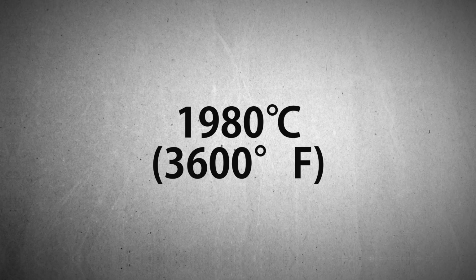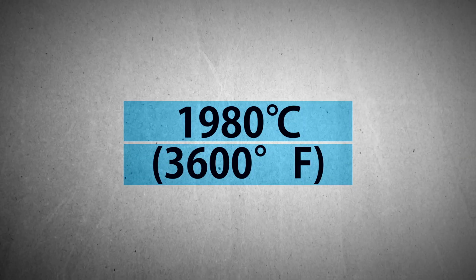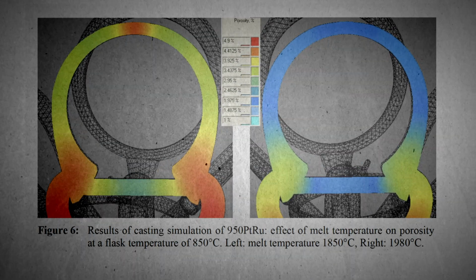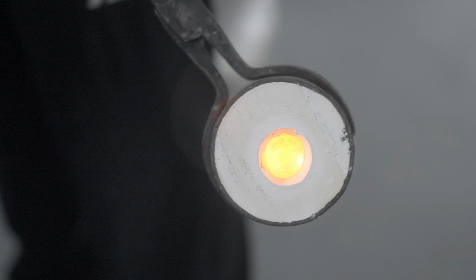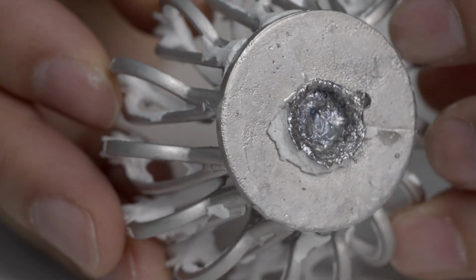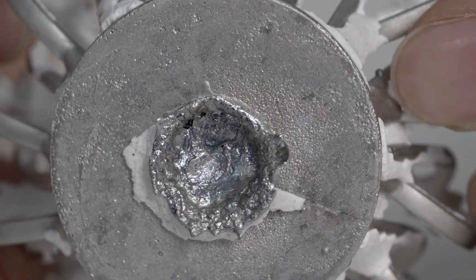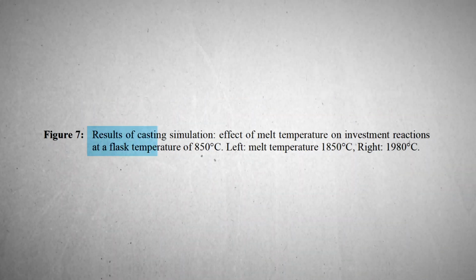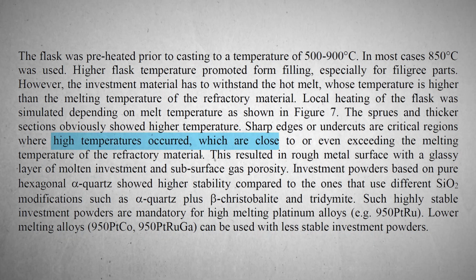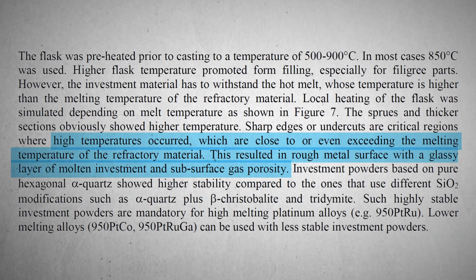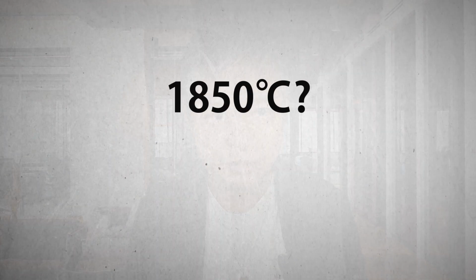So what does this mean? Figure 6 suggests that a higher temperature at 1980 Celsius, that's 3600 Fahrenheit, can reduce porosity, because when casting at a lower temperature, the entire piece cools and the heat is not as well maintained within the casting. Hence, it will increase the chance of shrinkage porosity, especially near the sprues. But figure 7 suggests that a higher temperature could result in higher reactivity with the investment that could result in rough surfaces. So the question is then, do we cast platinum ruthenium at 1850 Celsius or do we cast it at 1980 Celsius? Which is it? What do we do?